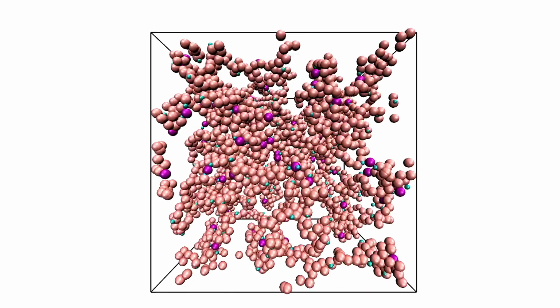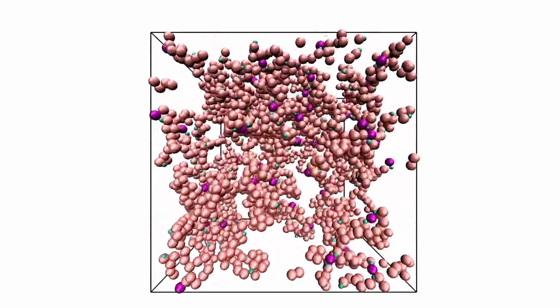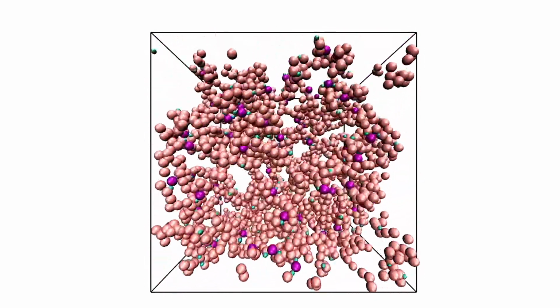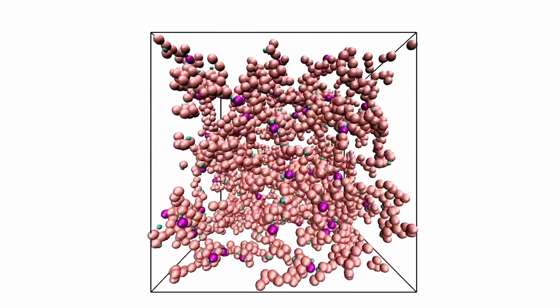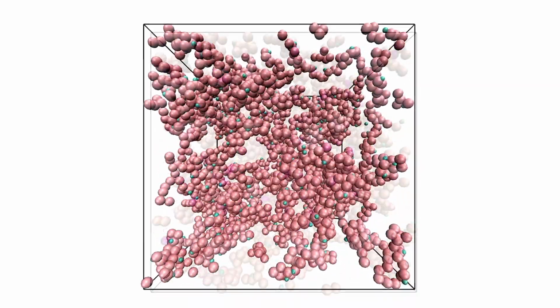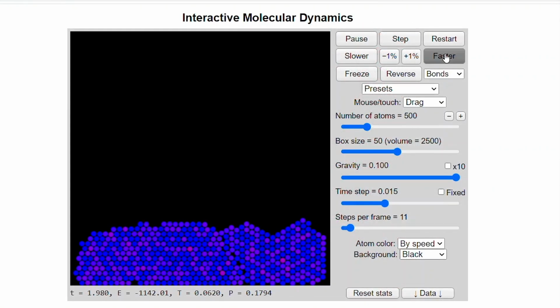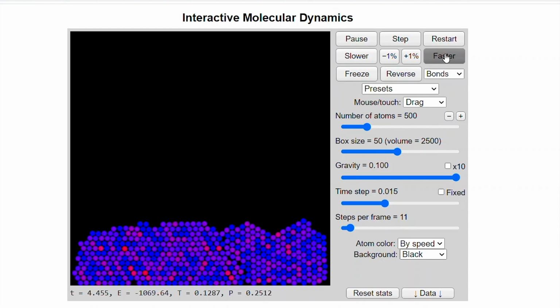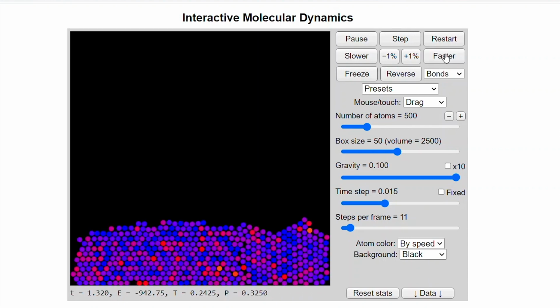Now, for example, we put a bunch of these polymers and borax molecules together. We can measure how each polymer moves and use that information to calculate the relaxation time from the simulation. When we add different amounts of borax in our simulation, we can see a similar trend that Sean saw in his experiments. Often, it's difficult to get an exact match to experimental measurements, but we can get an agreement in trends and a better understanding of what's happening at the molecular level. To get an accurate match, we need a more accurate model for our simulation, but this tends to come at the cost of the simulation taking a lot longer.